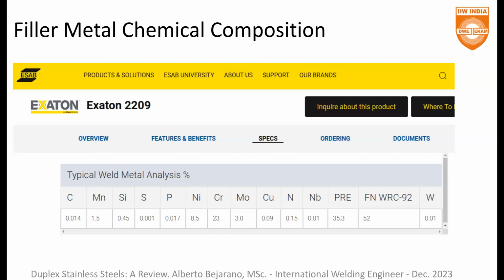Okay. So we have even less carbon in order to limit the probability to obtain carbides. Remember that in this case, we have a problem with stainless steels, which is sensitization. Sensitization means that in a specific zone, the chromium that should be used in the protective layer was used to construct a chromium carbide.